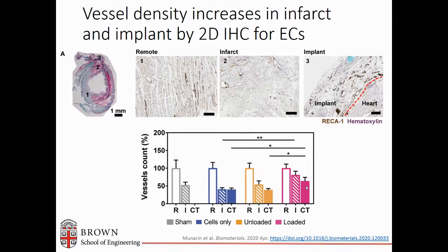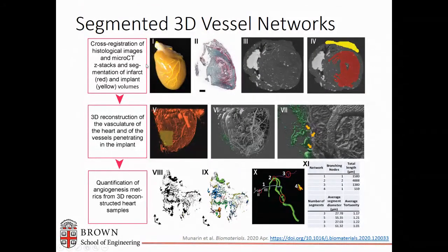This is a two-dimensional metric from histological images, and this is often what we see in the literature. But we raised the bar, and what we did was we did perfusion at sacrifice with a radio-opaque dye called microfill, and we did micro-CT imaging at a 10-micron voxel size. We then took histological images to be able to trace the infarct in multiple slices, and then register that with the micro-CT images and also the implant on the epicardial surface. So then we could segment this 3D network, be able to look at sites of anastomosis, or rather invagination of the vasculature into the engineered tissue.